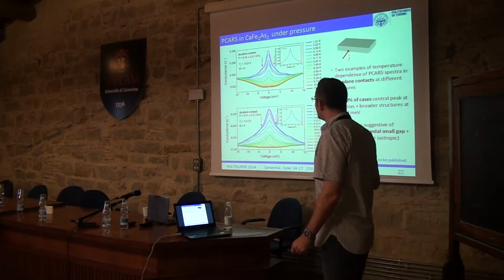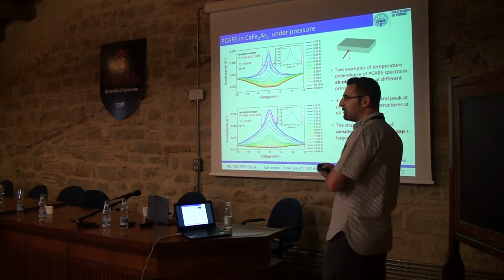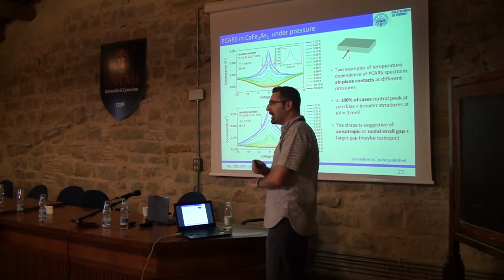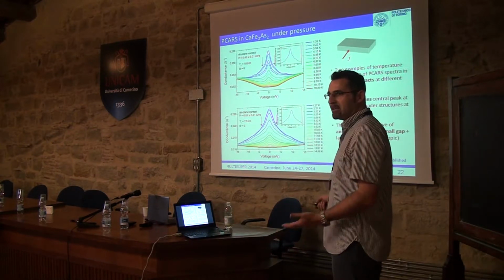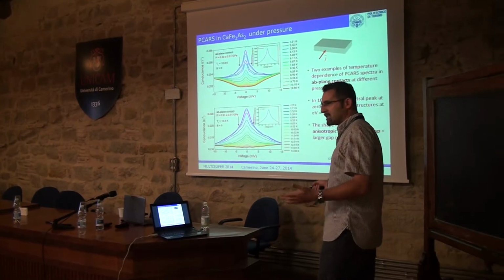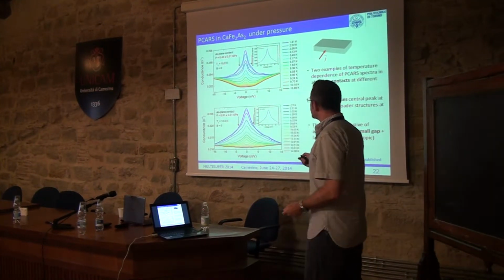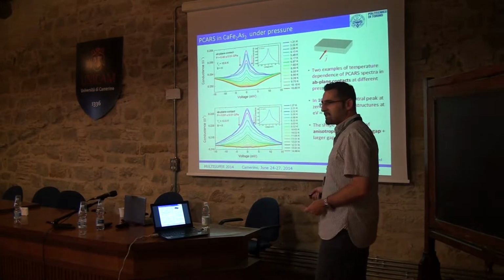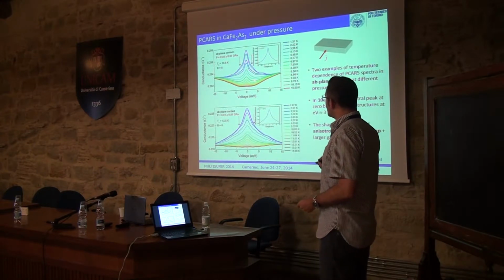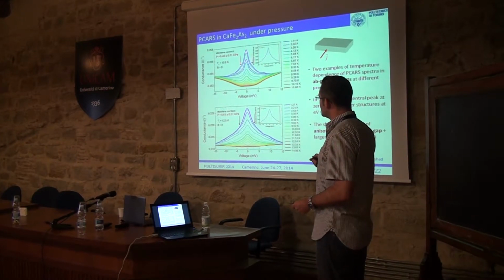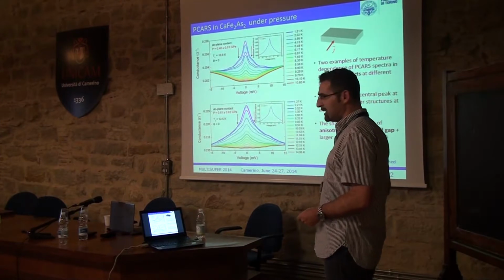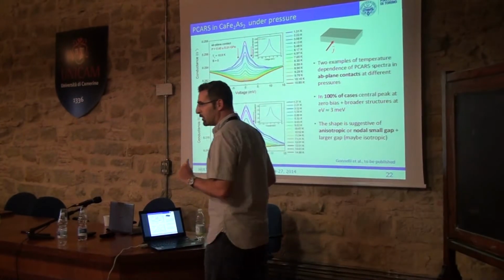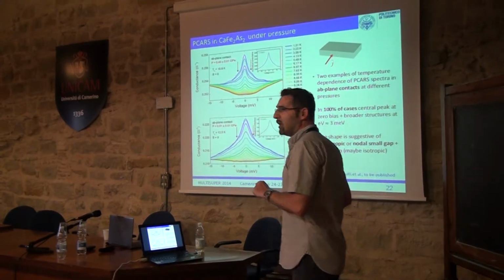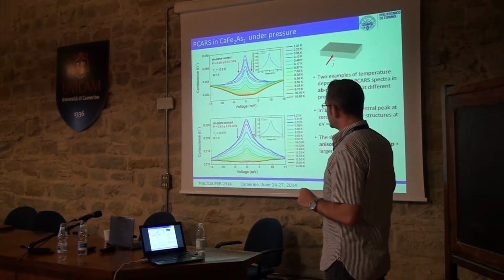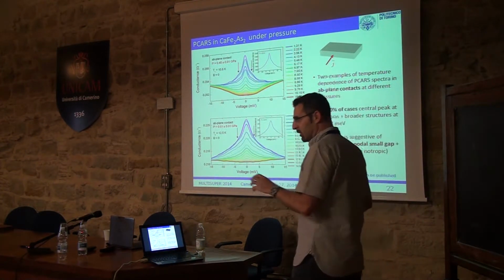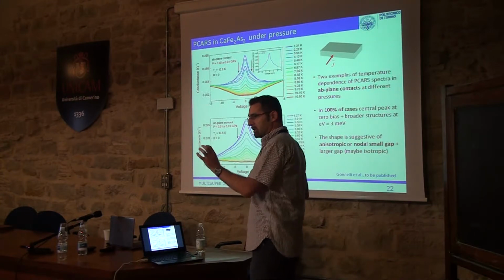These are two examples of spectra. As far as I know, these are the first point contact spectra ever taken in a sample under pressure, because the mounting is absolutely not trivial. This is for 0.4 and this is for 0.6 gigapascal. You see that all of them show a zero bias maximum plus shoulders. This is very similar to what I have shown before. By the way, the current here is injected along the ab plane. This is suggestive of an anisotropic order parameter.